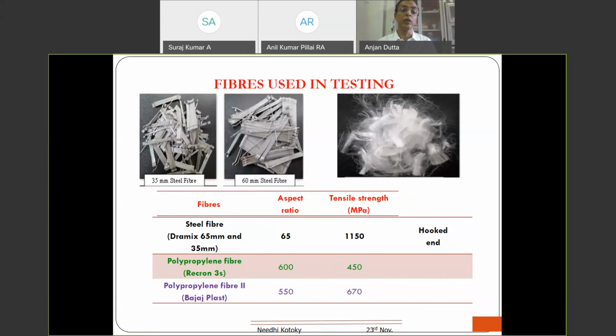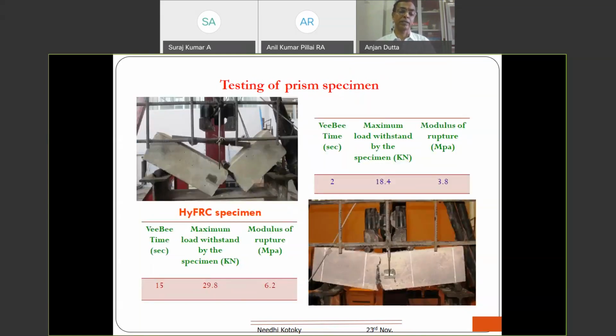To begin with, we took the test at the prism level, and if you look at the failure pattern of a prism without any fiber, it is brittle. Obviously it is brittle, no reinforcement, it is highly brittle. Now when you use those hybrid fibers, you can see that even with much higher load, 29.8 versus 18.4, the modulus of rupture is also much increased. So this is the motivation. You can see that the ductile behavior of the concrete will be much higher now, which is otherwise very brittle without any reinforcement, and that is why we use reinforcement.